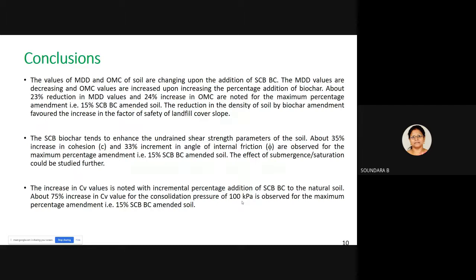So based on these test results, these are the main conclusions we have arrived at. The values of maximum dry density and optimum moisture content of soil are changing upon the addition of the sugarcane bagasse biochar, with MDD values decreasing and OMC values increasing upon increasing the percentage of biochar. About 23 percentage reduction in MDD values and 24 percentage increase in OMC are noted.